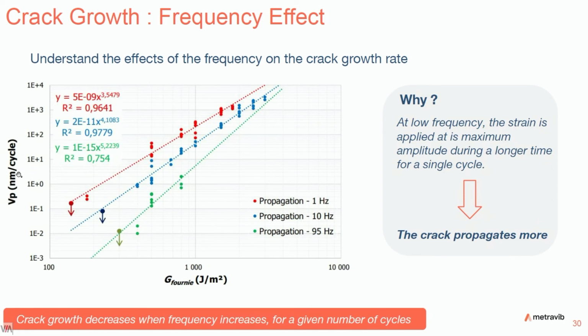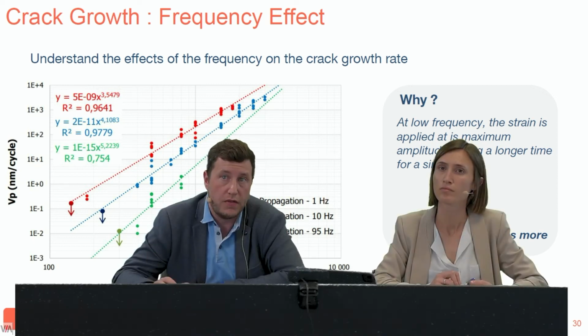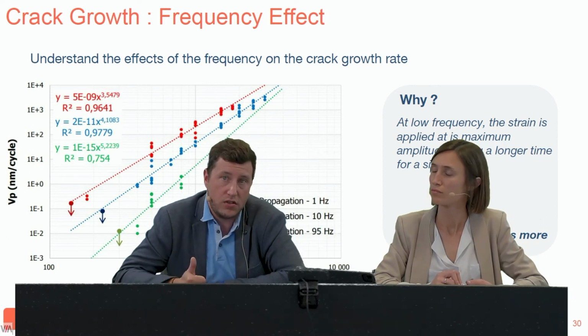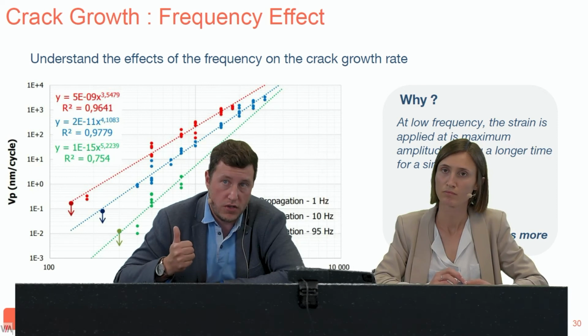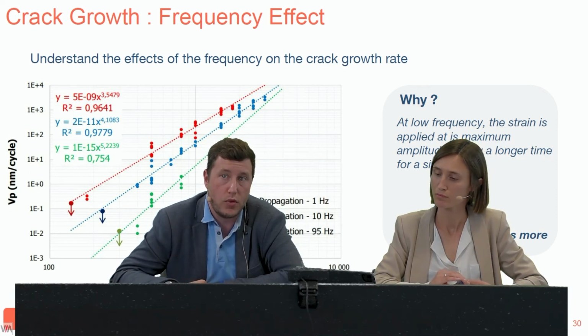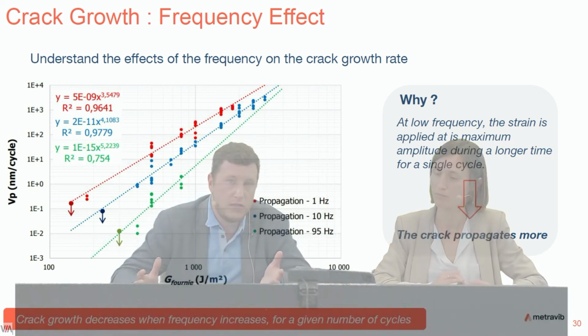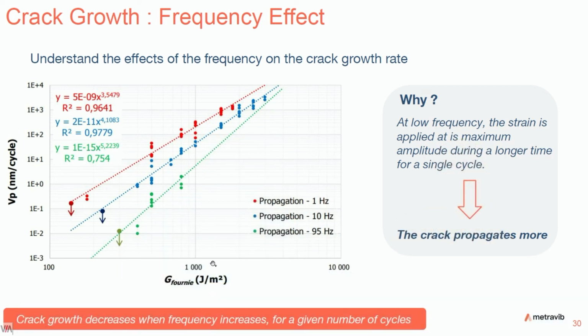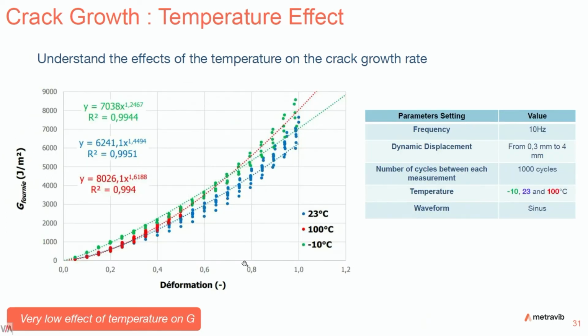However, what about the crack growth rate? Of course, crack growth per cycle decreases when frequency increases. Why? Because at low frequency, the strain is applied at its maximum amplitude during a longer time for a single cycle. So for just one single cycle, the crack propagates more. But in relative time, of course, the length of the crack is much higher at high frequency than at low frequency. But for one single cycle, it's not the same conclusion.